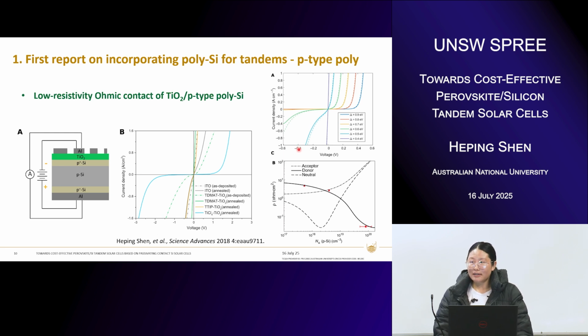So then we moved on to understanding the mechanism behind that and tried to correlate our experimental results with our simulation results. And we found there are a few important physical parameters that make this behavior possible. The first one is the energy alignment between the titanium oxide and the silicon, particularly the energy difference between the conduction band of the titanium oxide and the valence band of the silicon. So for that energy difference, delta here, we find that when this energy level difference is low enough, it tends to give us a low resistive contact.